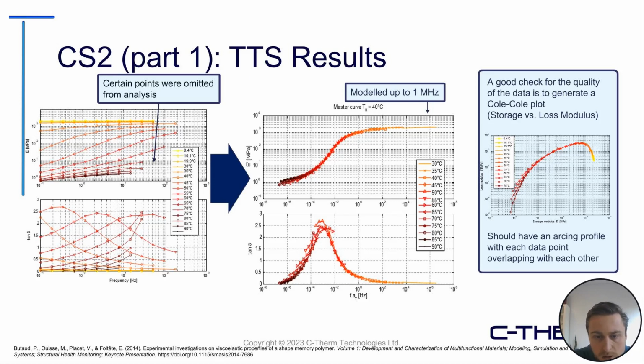Essentially what they were able to do, if we look at the arrow to the right here, is model performance up to 1 megahertz. This can be done by using equations or visually inspecting and shifting your data sets over one another until there's good overlay with each other. What they're able to do is measure up to 1 megahertz with a master curve at a reference temperature of 40 degrees, but you could shift this reference temperature to 20 degrees, 90 degrees, as long as it's within your temperature stages there.